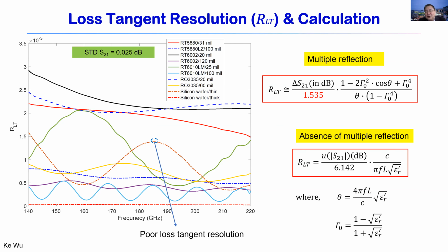Actually, for loss tangent resolutions, we developed two formulas. One is what we call the multi-reflection model based loss tangent resolution. Another is the absence of multi-reflection, as a single transmission and reflection, which also allows us to make the loss tangent resolutions. So in this case, we are able to get the modified formula for the loss tangent resolution calculations. There are two different formulas, but both can give us very good predictions about the accuracy of your loss tangent extractions.